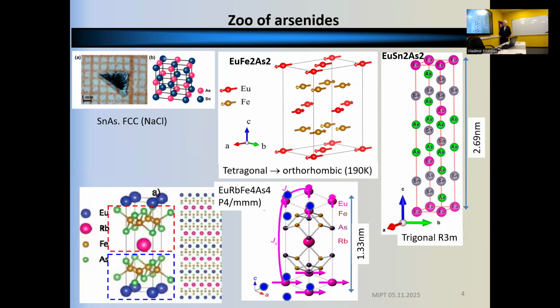The magnetism comes from the inner shells of europium. These are 4f cells, and in plane there is the largest exchange integral, and therefore in plane they are ferromagnetically ordered, but upon cooling, the interlayer exchange makes them antiferromagnetically ordered. Some of them, this is a kind of spiral antiferromagnetic states where the magnetic vector turns in some by pi, in some other by pi over 2, and so on. It doesn't matter at the moment.